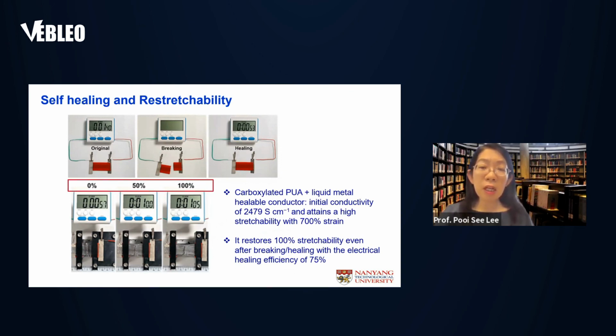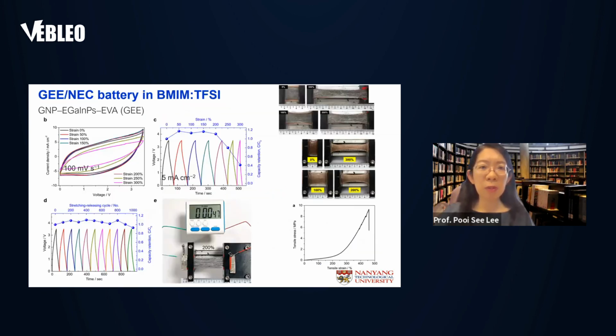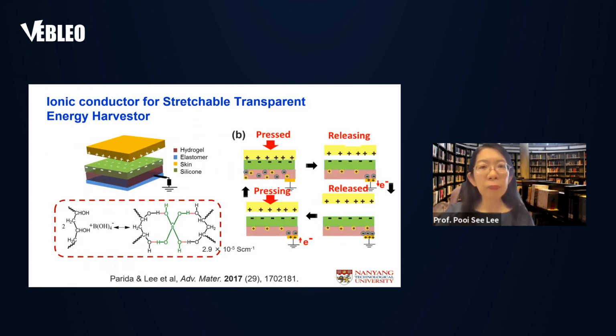So the healability of the current collector in the battery is shown here, which recovers 100% of the stretchability and electrical healing efficiency of 75%. Upon the full fabrication of the energy storage device, we can see here the performance in terms of strain. It is about 200 to 300% strain, and multiple stretching release cycles of the stretchable battery can be attained.